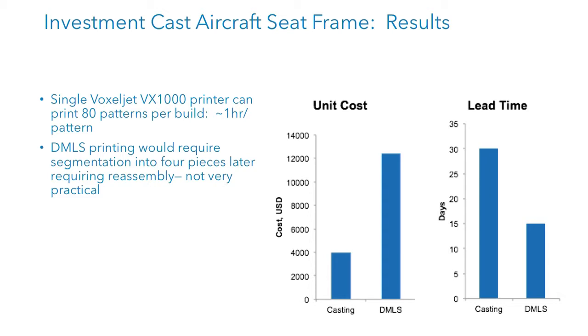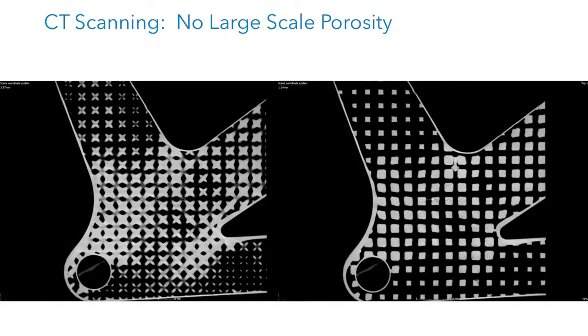That being said, typically you're quoted about 3-4 weeks for investment cast parts, but oftentimes if you pay an extra 15-20%, you can get turnaround times as low as 2 days. So it's pretty exciting. We also ran some of the castings that we did through a CT scanner and X-ray just to check for some of the traditional casting defects. What we're looking for here is porosity, which can manifest at a couple of different scales, but we're excited to see that there's no visible porosity using existing conventional inspection techniques. So we're pretty excited about that.